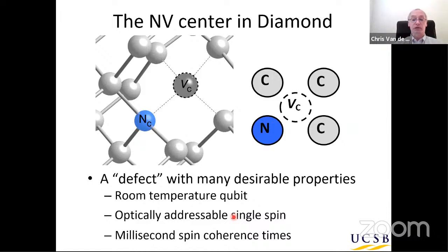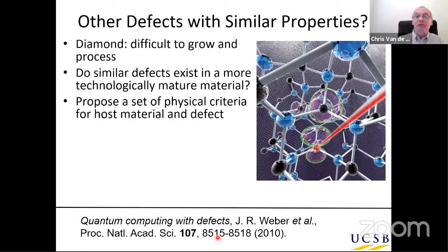And in terms of controlling that spin, coherence is, of course, very important. And for the NV center in diamond, millisecond coherence times have been demonstrated, which is essentially an eternity in terms of being able to manipulate those spins for actual quantum computing applications. So this is all extremely promising. Except for the fact that diamond is, of course, a very difficult material to work with. It's difficult to grow, it's difficult to process. Natural diamond is very expensive.